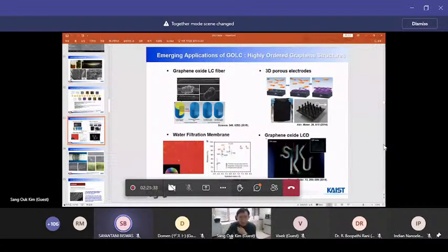But right after our discovery of graphene-based liquid crystal, many other research groups reported that other ways of graphene dispersion can also lead to a liquid crystalline state, and even dispersions of some other 2D materials like molybdenum disulfide, TMDs, or MXenes also show liquid crystallinity, and they lead to many interesting applications based on the highly ordered structure of 2D-based liquid crystals. So we are very proud to see that our discovery of graphene oxide liquid crystal really initiated the research field of 2D-based liquid crystals. And graphene-based liquid crystal is also interesting for many different material fabrications. Based on the liquid crystalline dispersion state, you can simply spin all-graphene fiber structures. So this is a very low cost counterpart to the traditional carbon fiber. And sometimes you can get highly